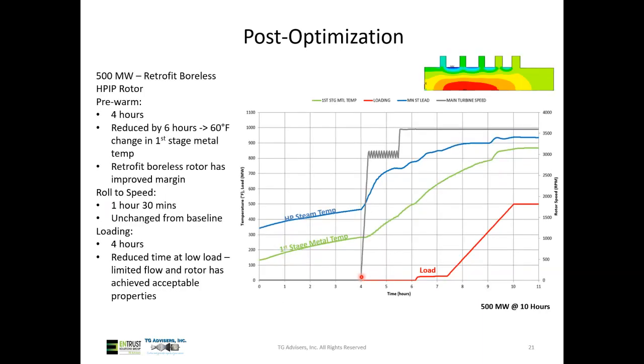So just wanted to show you some of the improvement. In this case, we were able to cut down the pre-warm process by 6 hours, and we only lost about 60 degrees in metal temperature. In some units, we would have accounted for that by adding the low speed hold, but in this case, it was a retrofit boreless rotor, so the stresses were significantly lower than the original design. So we kind of left the balance unchanged.